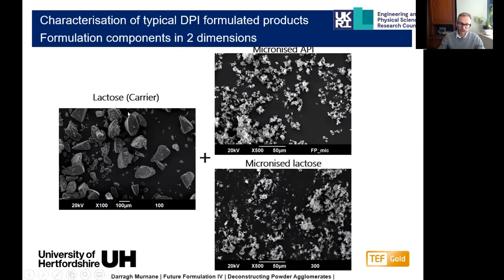So we have this large particle size carrier or diluent lactose. We'll typically have a micronized API. So this shows a number of larger agglomerates of very small individual drug particles. Those particles are between about 0.5 to 5 microns each. But we may also have extra micronized lactose within that formulation as a formulation aid. So up till now, it's been really difficult to see what this microstructure really is. And certainly it's been impossible to see the microstructure of undisturbed agglomerates, those agglomerates which are mixed with the lactose and go into the formulation.